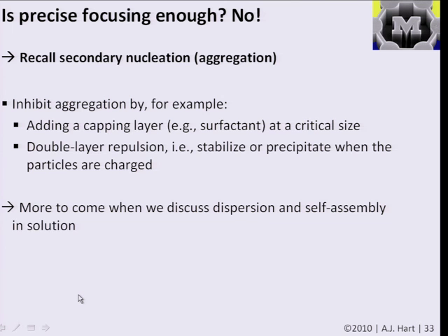In some cases, you can control the pH for charge stability in conjunction with the growth process, so you keep the particles physically separated to prevent agglomeration, to prevent aggregation, and also to make sure that all the particles get reasonably enough monomer from the solution by diffusion. And we'll talk more about that later.